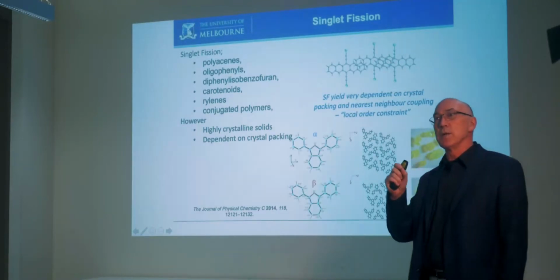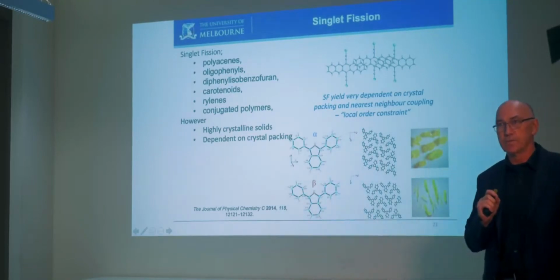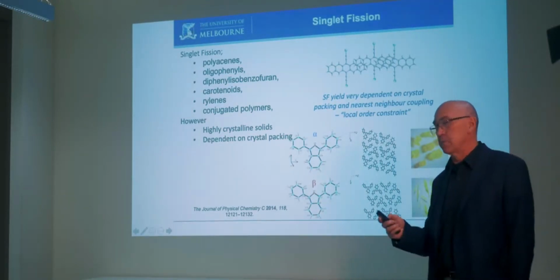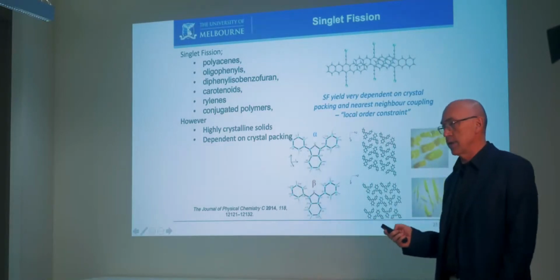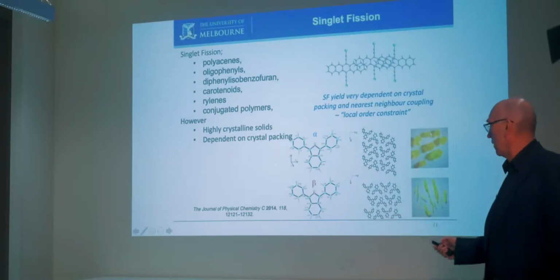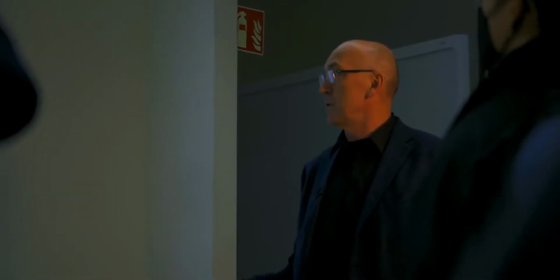So then we need to be able to control the crystallization of these materials if they're going to undergo singlet fission or promote singlet fission in a solid state. Now people have been looking at that and said, okay, we need two molecules, let's join them together. And so a lot of people have been doing a lot of work. So this is the pentacene, tetracene, join them together, see how singlet fission works. And we can do that with the diphenylisobenzofurans and all these other materials, putting bridges in. Most of this work has been done in solution. If you try to then look at these in solid state, they're no longer singlet fission active, or the singlet fission activity is very, very low. So we don't get that benefit.